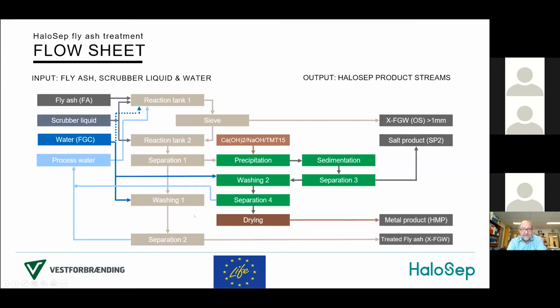And from that stage, it goes into a separation stage two for the final dewatering of the treated fly ash, going to the right in the bottom. If we go back to the separation one, we see the metals and salts in solution going into a precipitation stage. From the precipitation stage, we go into a sedimentation stage, and further into a separation stage number three, where we separate out the salt product, and the